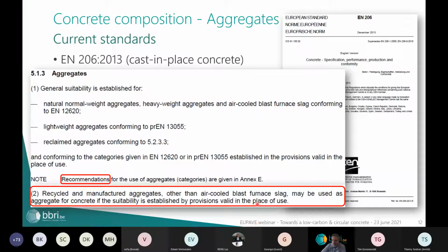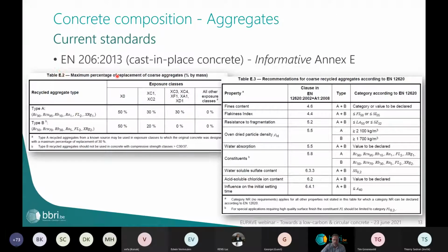In fact, the standard says you can use them, but the national annexes of the EN 206 have to individually allow or describe what is possible to do with these aggregates. When we look at Annex E in the EN 206, it's an informative annex that describes how to use regular aggregates, but also the recycled aggregates. And there we can see that there are some rules for the aggregates themselves to be used. Type A is the concrete recycled aggregates, and type B is the mixed aggregates. So there are some demands regarding the composition of these aggregates. And then there is also the percentage in which we can replace the natural coarse aggregates. And you can see we only speak about the coarse aggregates.